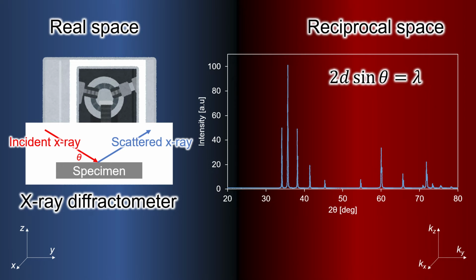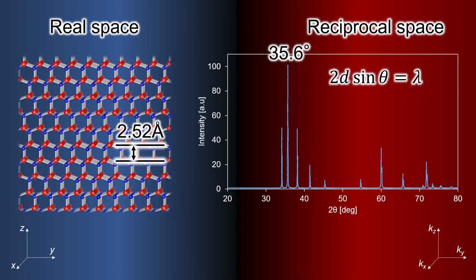We can find the peaks when the angle of incidence, theta, and the plane spacing, d, of the sample satisfy 2d sin theta equal to lambda. Lambda is the wavelength of X-rays. You can use this formula to calculate the plane spacing, d, from the peak position. For example, the strongest peak is at 2 theta equals 35.6 degrees and its plane spacing d can be calculated as 2.52 angstroms.